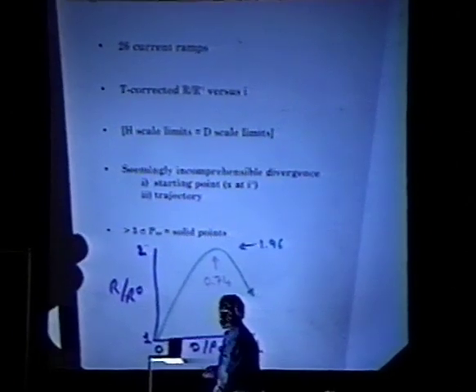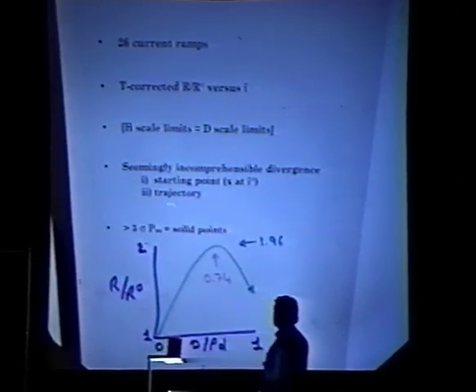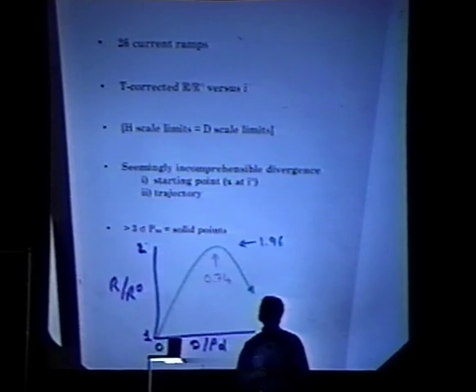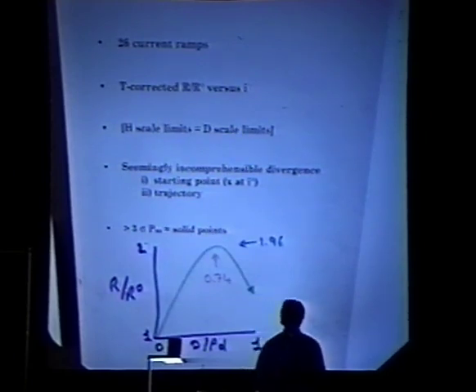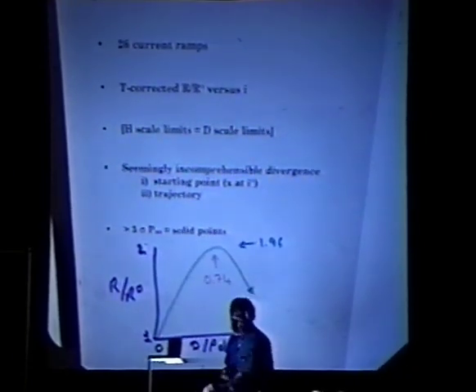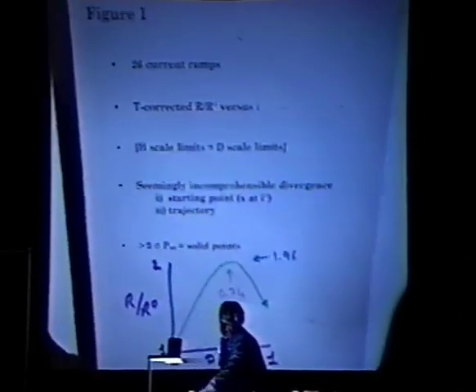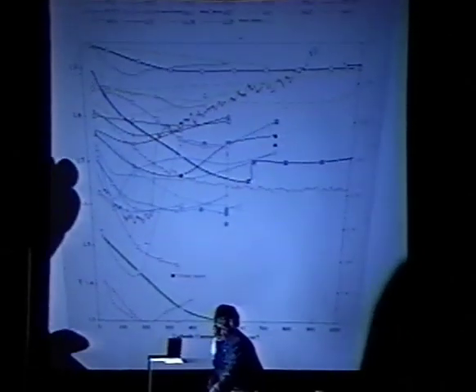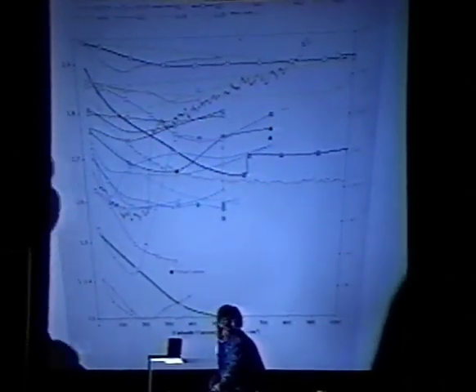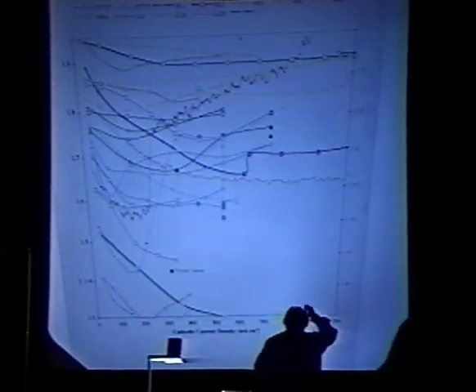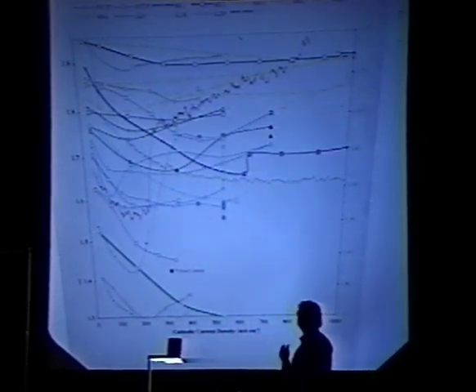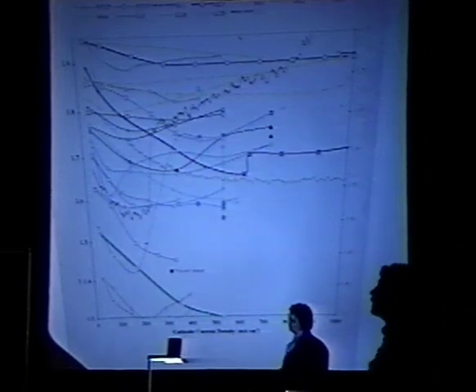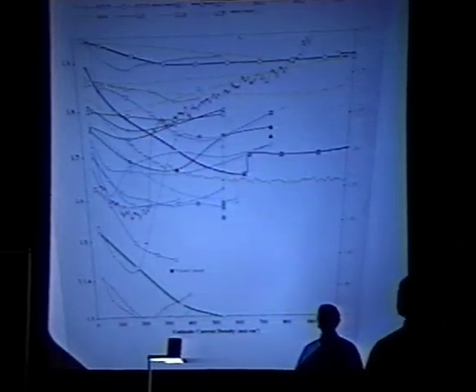In this curve that I'm about to show you, the points that are solid are those for which we observed excess power at more than a 3 sigma confidence level. All other open points, no believable excess power was observed. Okay, this actually is a catalogue of failure, if you like. Well, the first interpretation of this slide is that the SRI group is incompetent.